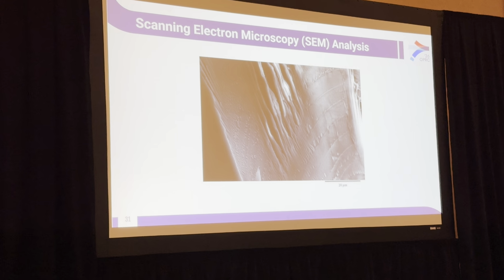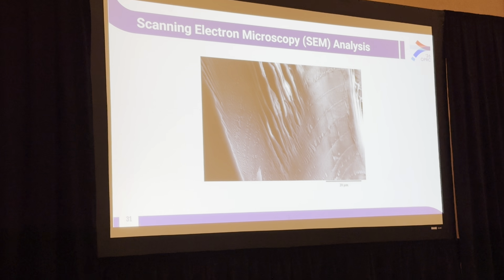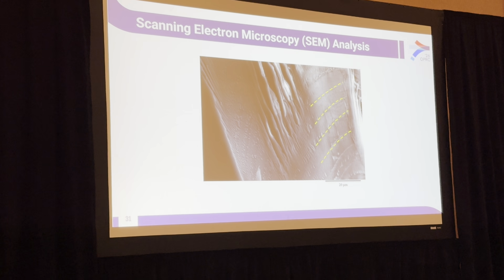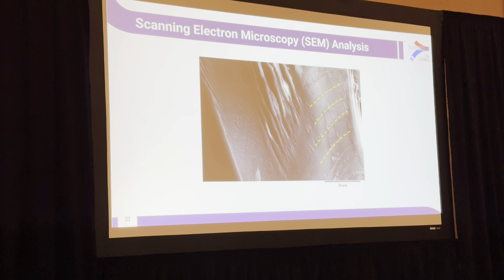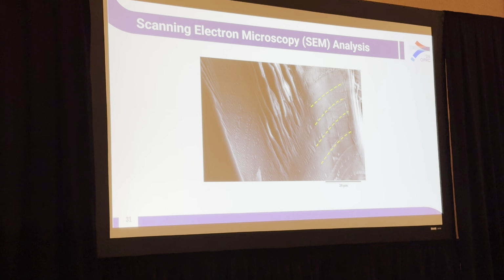Here, this image looks very closely, and I want to highlight, if you see these concentric bands here further on the right side of the image, highlighted in yellow, these concentric bands tell us that it is fatigue failure, it's the repeated loading that caused the failure within the socket. It's not the static one big load, it's that repeated loading that's causing that fracture.